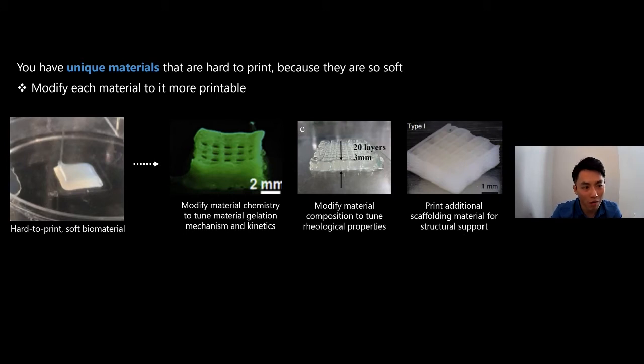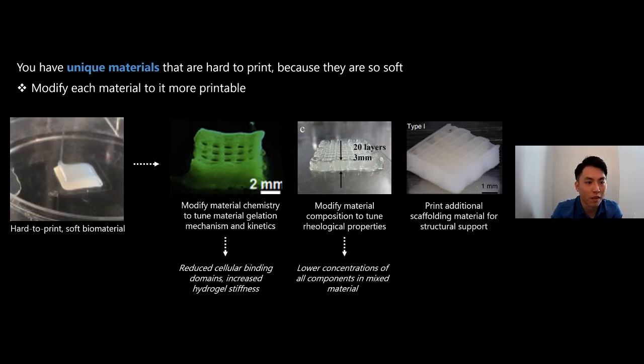Another way of addressing this problem of printing a very soft biomaterial is that you can print additional scaffolding material to provide your soft material with structural support, right? So each of these things really come with their unique challenges. So for example, when you're modifying material chemistry, you lead to oftentimes reduced cellular binding domains, and then also increased hydrogel stiffness, and then also a lot of times reduced biocompatibility with the modification to the materials. When you're adding in additional components to your ink or to your material, you're lowering the concentrations of all components in the mixed material as a whole.